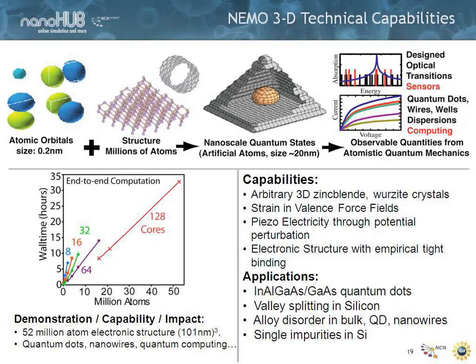So we don't do a true relaxation in the thermodynamical sense where bonds can change and all that. Also, we can do excitons in principle as a perturbation approach. So if we calculate the eigenstates of our system, we can then calculate direct and exchange matrix elements for excitons, and we do that. Those are the fundamental things we can do towards that realm.